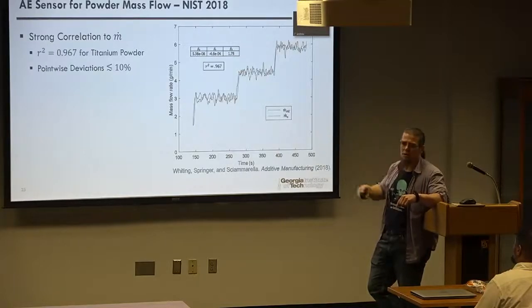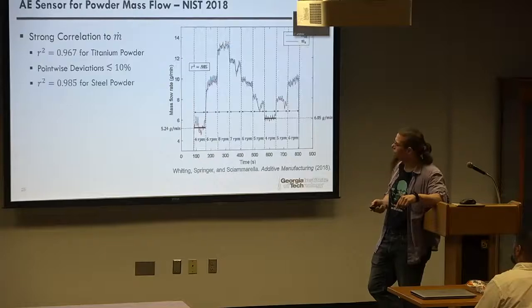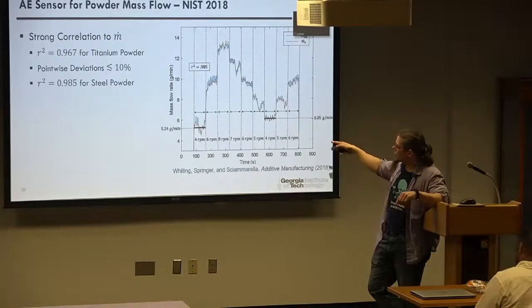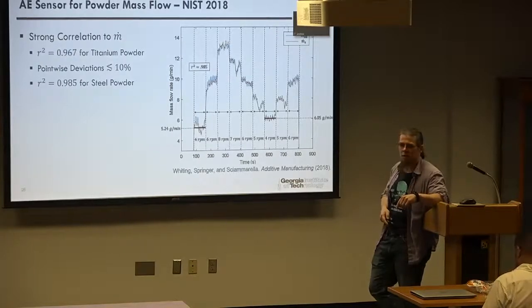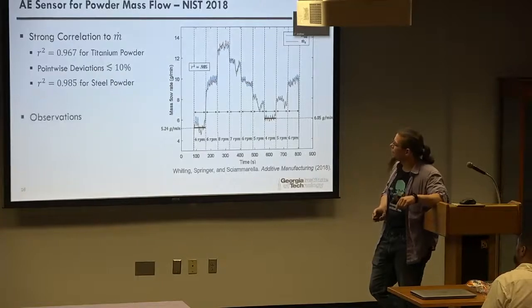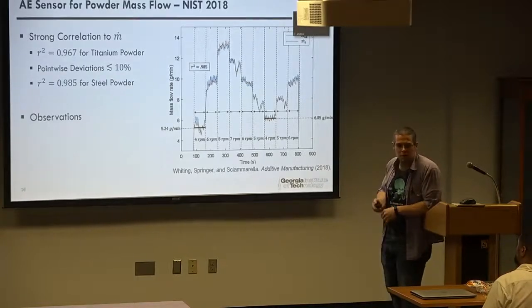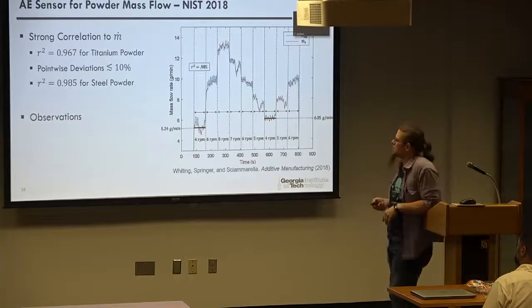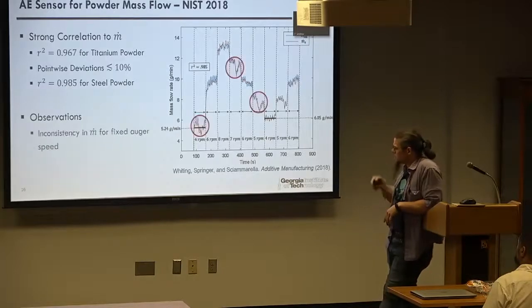Point-wise deviations are on the order of about 10% or less. So not horrible, but not great if you're actually trying to use it for feedback control. For steel powder, they got a slightly better correlation, but they were still looking at a similar point-wise deviation. They had some interesting observations, which kind of reinforced the need for developments in this particular sensor space.